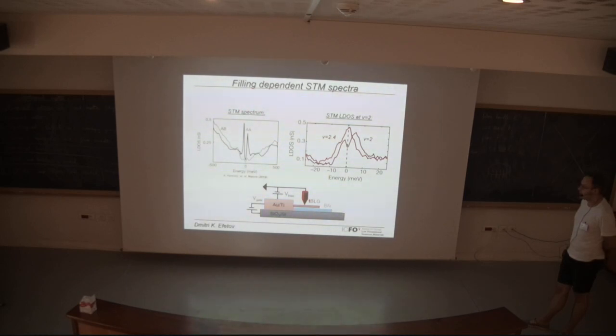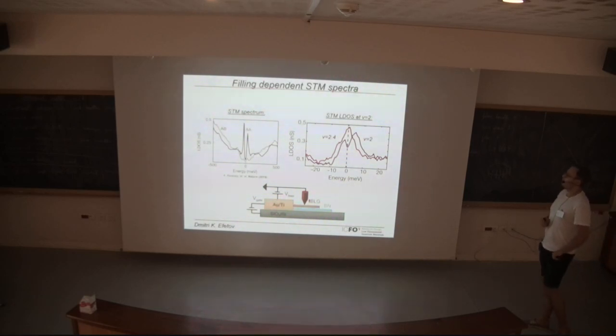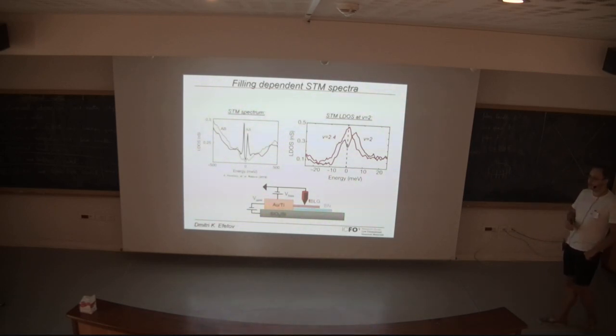But what they can say is that this gap really seems to appear only at integer filling, and this gap also does not exist in devices away from the magic angle. So when you create a twisted bilayer graphene system at 1.3 degrees, away from the magic angle, where even from the single particle picture you don't get flat bands, you're not expecting interactions, they're not seeing this type of dip. So this is the evidence which we have at hand right now that something is going on.